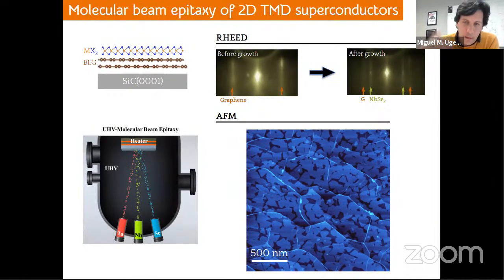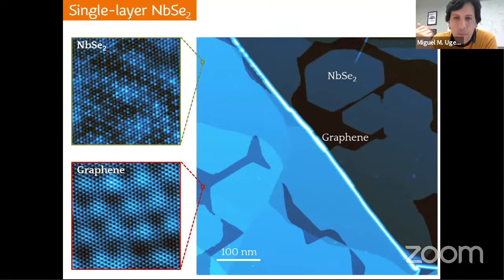After this growth, in order to optimize the recipe for niobium diselenide and other TMD materials, what we usually do is take these materials to the XPS or the AFM in order to control and optimize the morphology of the material. Here I show you a large-scale AFM image taken in ambient conditions of one of these samples of niobium diselenide. Here I show you the large-scale morphology of one of these samples.